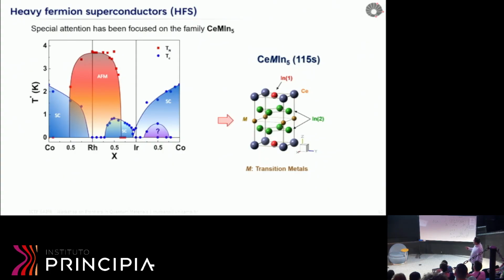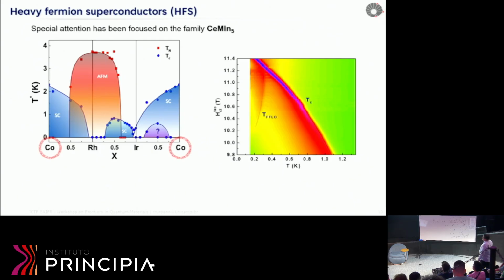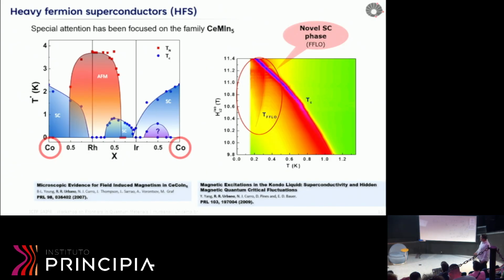So as we can see in this phase diagram here, it's pretty rich. If you change M here, using cobalt, rhodium, or iridium, we can find many different ground states. Some of them superconducting, some of them magnetic. So the first one, if you look at cobalt here, I'm not going to explain in detail, but I would like to mention, because it was very important at that time, this novel phase of superconductor, the Fulde-Ferrell-Larkin-Ovchinnikov state, that was found in these materials way down there in temperature, millikelvin temperatures. And we also did some work on that, especially myself, I did some NMR work, and we could contribute. If you are interested in some results, you can check these papers here.